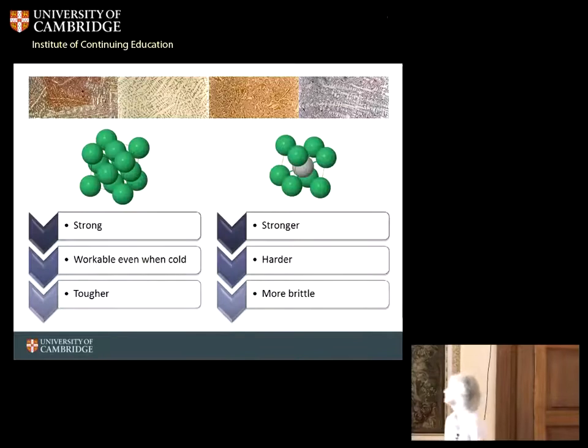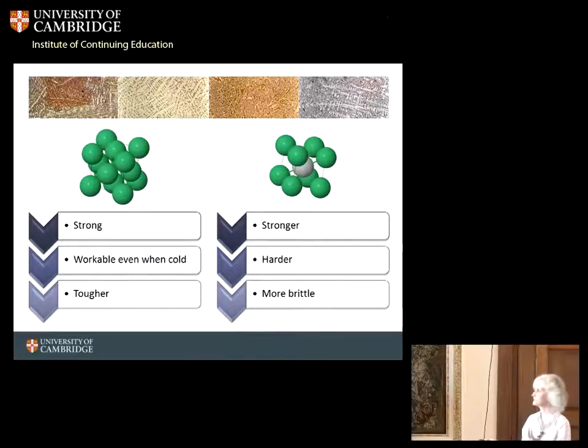So, what have we got? We've now got two slightly different structures. One can accommodate slightly less zinc, one can accommodate slightly more zinc, and any real structure is some kind of combination of the two of them. Now, our basic face-centered unit gives us a material which is strong. We can work it, we can shape it, we can hammer it, even if it's cold, and it's fairly tough. The body-centered structure, which has a little bit more zinc, more like 40–45% zinc, gives us a material which is stronger. It's harder, but it's more brittle, and that means that we can't work it effectively, even when it is hot. What we have in a real brass is the structure organizes itself into a combination of these two, and that gives us a kind of composite material.